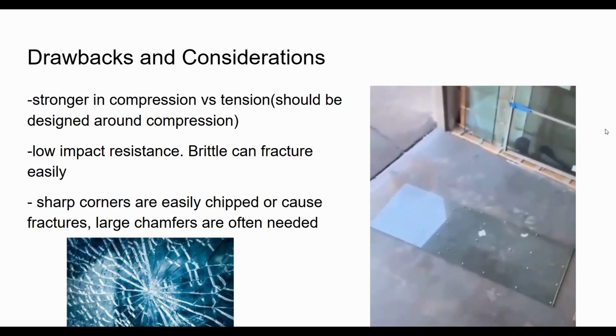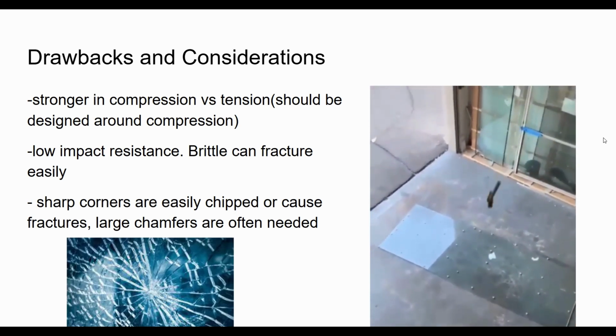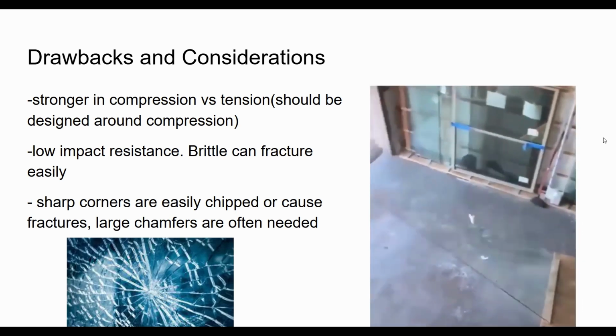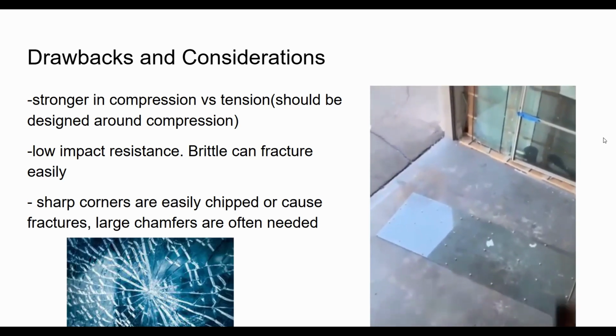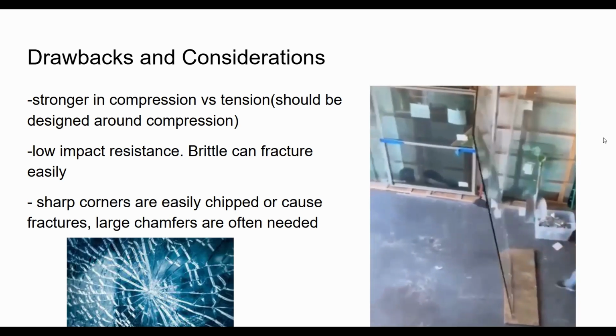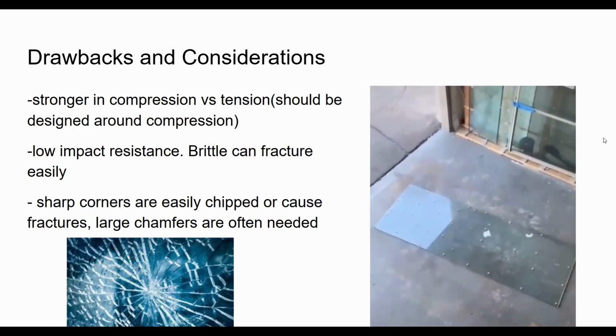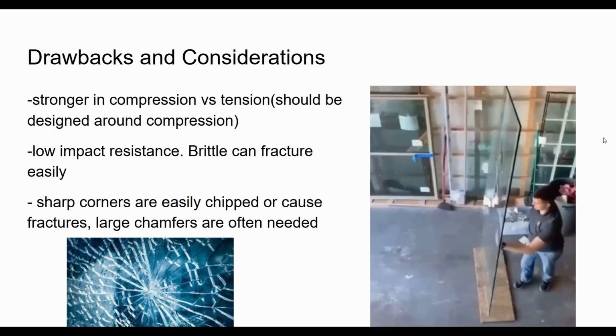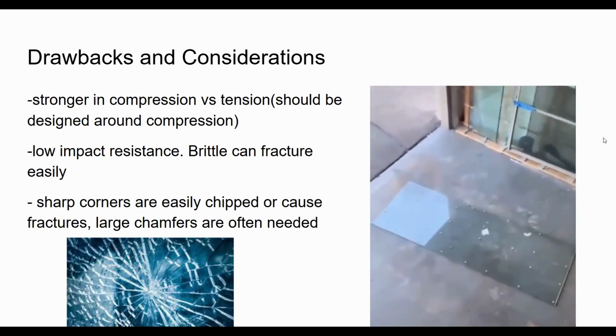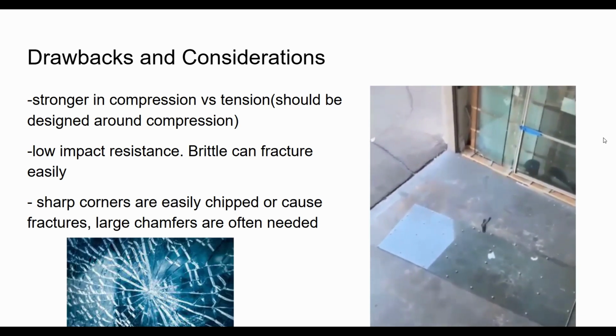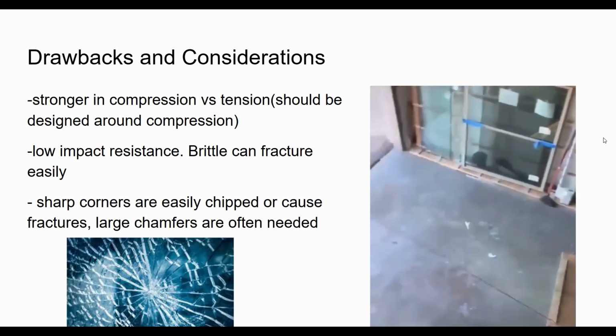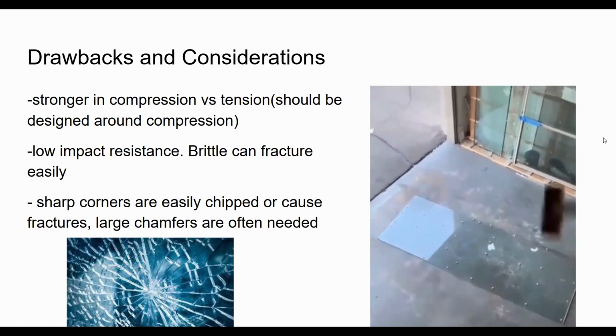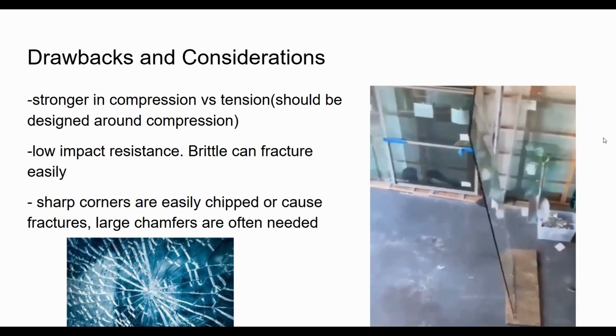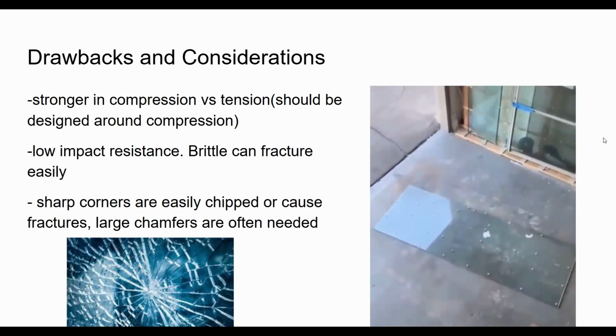So that's another thing to look out for. Having sharp corners on edges of glass is a really good way to make high stress points very, very focused. If you notice when you have a coffee table with glass on it, they always chamfer the edges to spread out the force that would have hit that corner and evenly distribute it, to reduce the amount of cracks that could happen when it bumps into it.